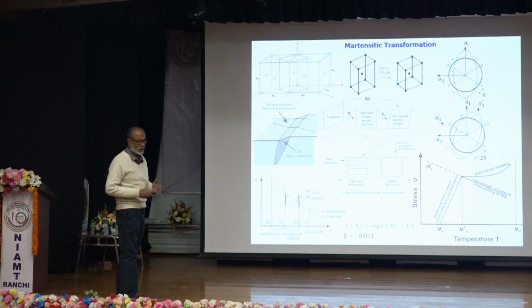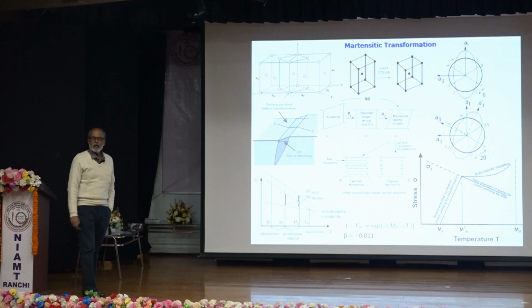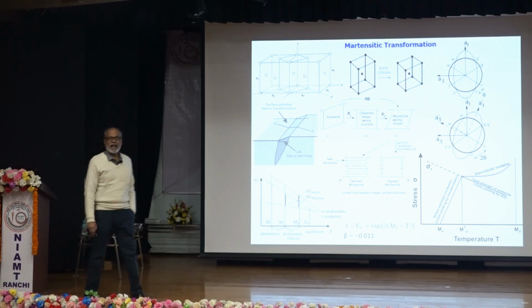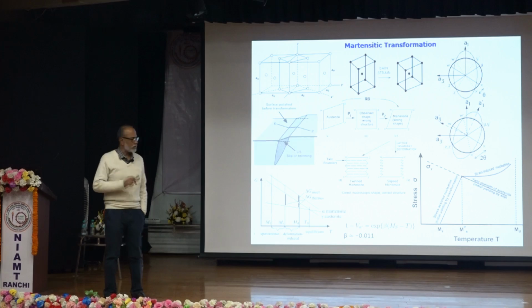If we apply a shear, we generate dislocation, and this dislocation moves from one into other. And when dislocation moves from one into other, the atomic arrangement within the crystal is not changed. That we know from basic metallurgy. The atomic arrangement remains same. So lattice remains invariant, right? But the shape can be reorganized either by dislocation or by twin. So that we call invariant lattice strain.